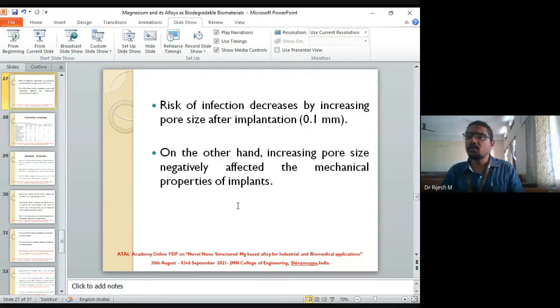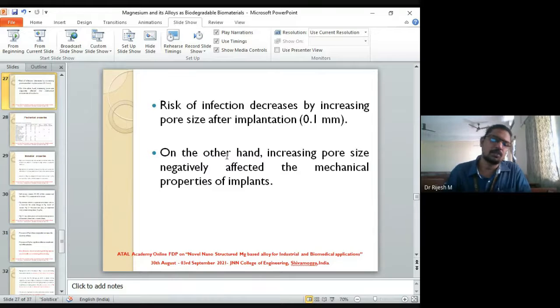So what happens is the risk of infection is decreased by increasing pore size after implantation. So if the pore size is very high and if healing is very fast, the risk of infection is decreased to a large extent. But the only problem where we need to restrict the increase in pore size is that the mechanical properties of the implant come down if the pore size increases. The mechanical strength of a porous material is not that great, not good. So this has to be optimized.